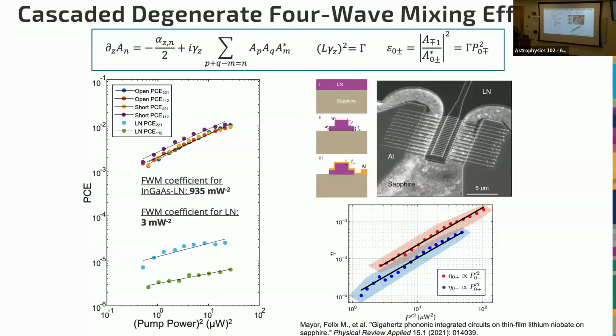So if we just take our focused acoustic waves, it's not quite as good. We just shoot them through lithium niobate, and so they're just not as focused. So it's basically the same as this demonstration, but they're not quite as tightly confined. Then we get something like 3 per milliwatt squared, right? So that's just saying that if you confine them a little bit more, you get higher nonlinearity. But basically, this is all the nonlinearity from lithium niobate alone, right? Just that lithium niobate is a little bit acoustically nonlinear.